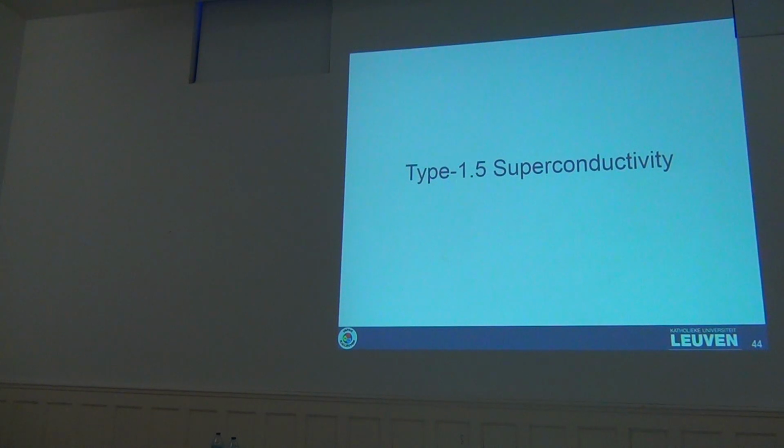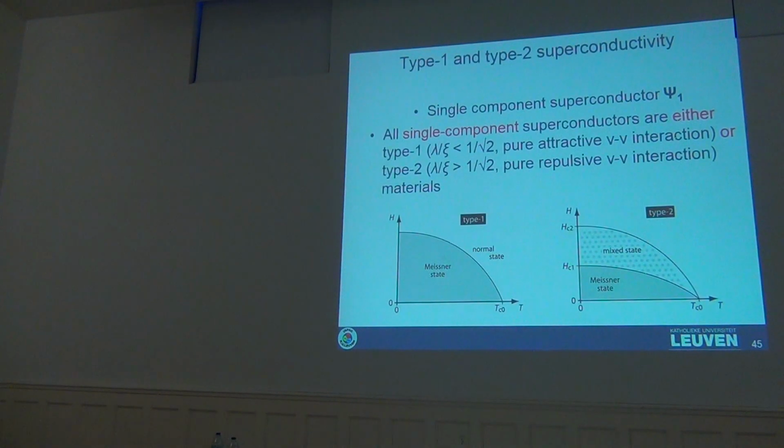And then you can also model this MgB2 sample. I'm already anticipating in which material you can see it. And then you can see neither type 1 behavior nor type 2, but something in between. Theoretically, it was predicted by Egor Babaev, and then further elaborated by him with his colleagues. They predicted that in certain materials, if you have a multi-band superconductor, and if one band attempts to be in a type 1 state, another in type 2, then you can have a unique situation, which is called type 1.5.